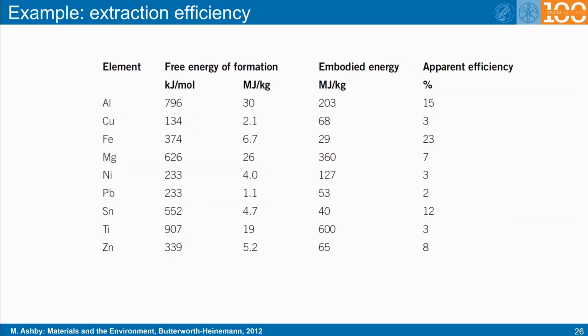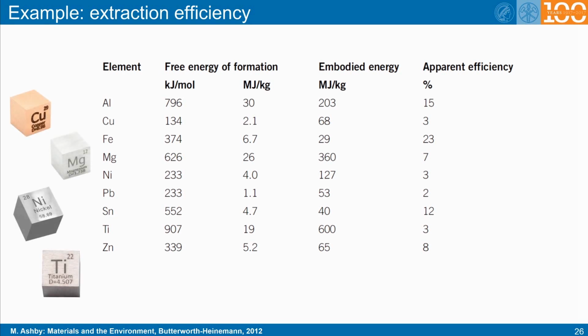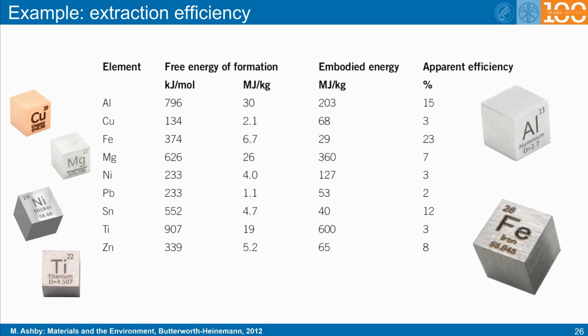This slide shows the embodied energy and the extraction efficiency for a number of metals. We learn that for aluminium and for iron, the apparent efficiency, compared to the free energy of formation of the ore, that is, the thermodynamically embodied energy, is still relatively decent, relative to the other metals that are shown in this table. The number of 23% that is shown here for the apparent efficiency of the synthesis of iron, is even smaller than the one that was given on the preceding slide for the case of hematite. This deviation is due to the fact that the number shown on this page averages over both types of ores that are used for making iron, namely, hematite and magnetite.